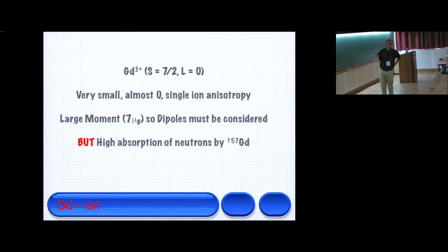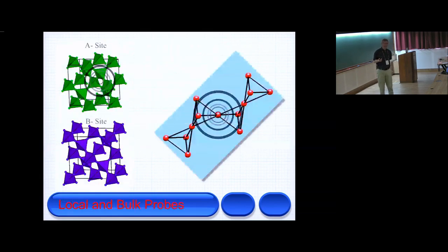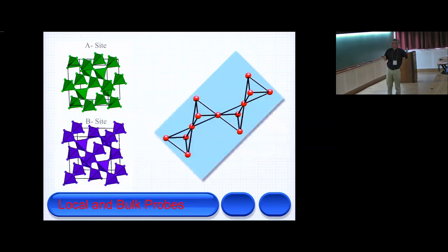The anisotropy, the single ion anisotropy of gadolinium, in most of our classes we'll say is 0. But when we really look at it, it depends on the environment. Back to crystal fields. And the rare earth environment of the pyrochlores is trigonal. So actually it can be significant anisotropy.